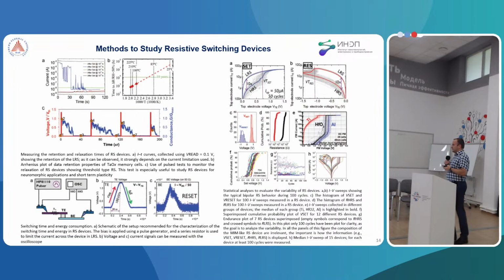The next test is measuring the retention and relaxation times of the resistive switching device. We measure current-time curves by using a common voltage of read operation, typically 0.1 volts, showing the retention of the low resistance state, as can be observed, strongly dependent on the current limitation.